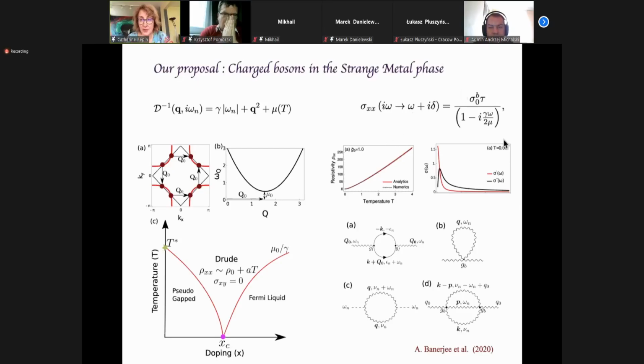So very fortunately, we nicely got linear temperature dependence in 2D for these charge 2 bosons, and also a quasi-Drude conductivity, so linearity for the Drude. So this was very encouraging. So now we're trying other types of techniques like the memory matrix, which is a bit more like a hydrodynamic technique rather than the Kubo. Since the bosons are very incoherent, it's difficult to have a Boltzmann treatment of them.